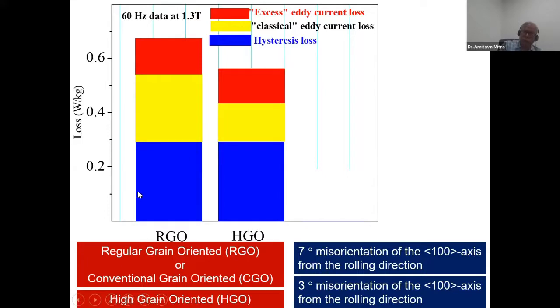One component comes only from the magnetic contribution. One part comes from the eddy current, called the classical eddy current. One is called the excess eddy current. This excess or classical eddy current can be reduced further by increasing the resistivity of the material. When we go to the amorphous stage, since these materials are randomly oriented, the scattering of electrons takes place more compared to crystalline material.